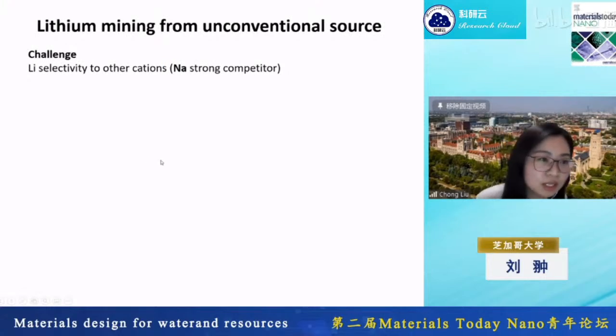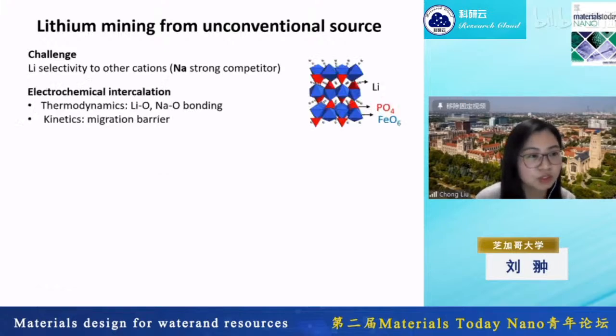So sodium is a critical competitor to lithium because they are similar, but sodium is just a little bit larger. The way we try to develop is we want to see whether an electrochemical platform can help us to extract lithium. And we want to see the selectivity of an electrochemical intercalation reaction, meaning that you want to see whether lithium or sodium is more preferred in a confined structure in a crystal.